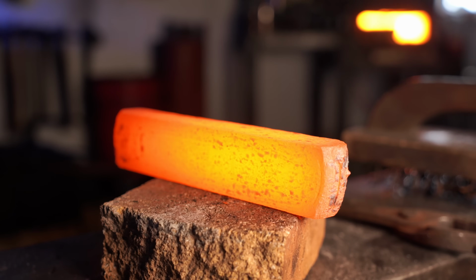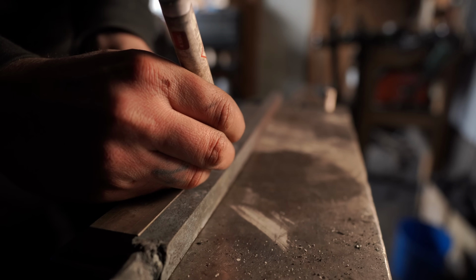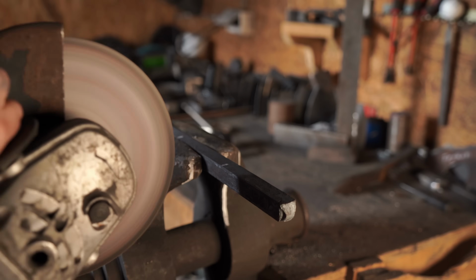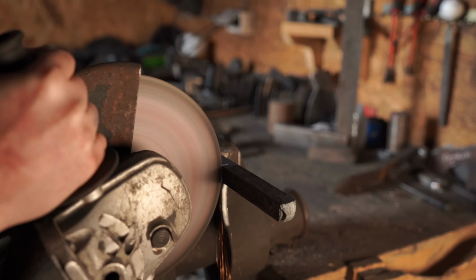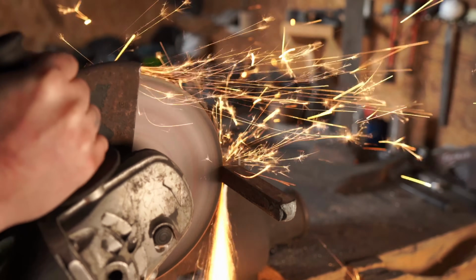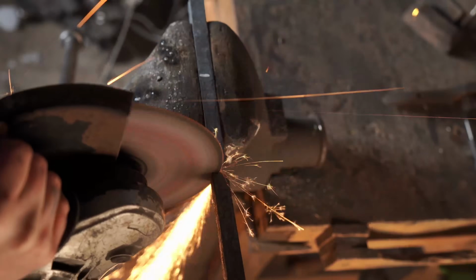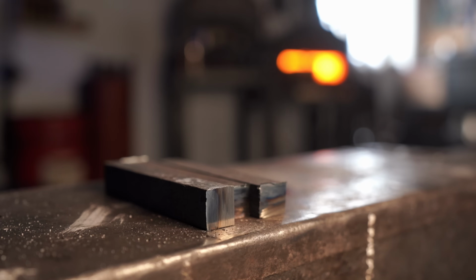So the 90 layer billet is now complete. Now, I did actually make one more billet in between heats. Not 90 layers, just the original 24. I quickly forge welded that together and drew it into a square bar. The idea is to cut it into 4 pieces and use them for the edge steel.